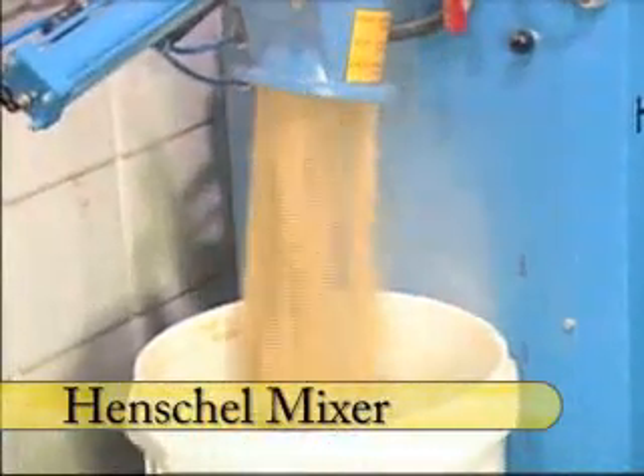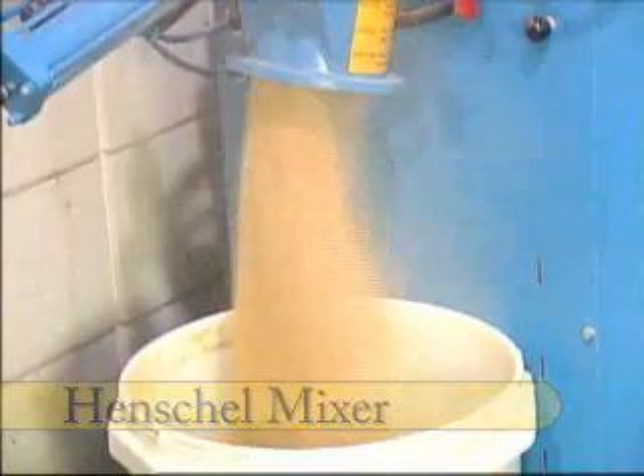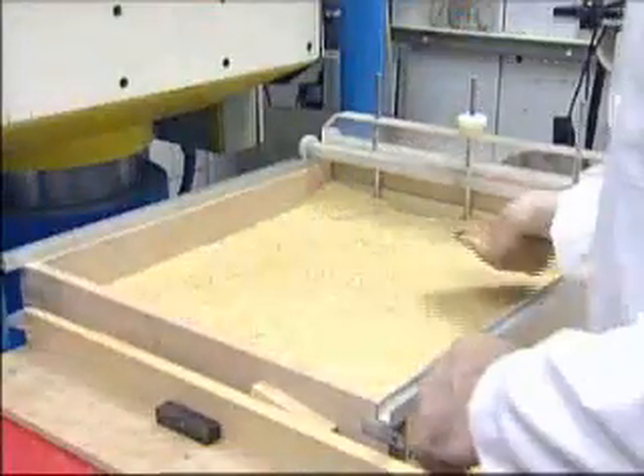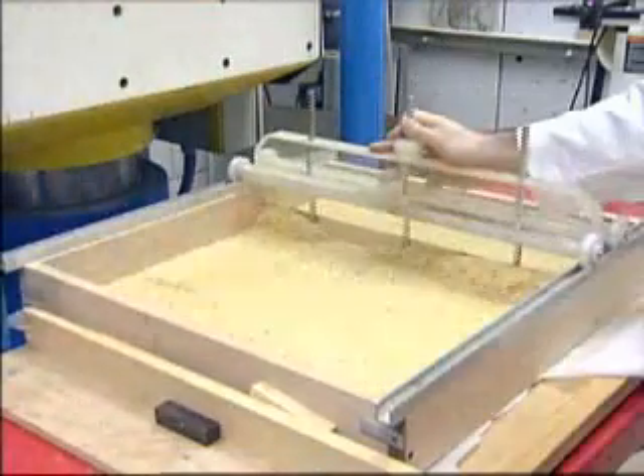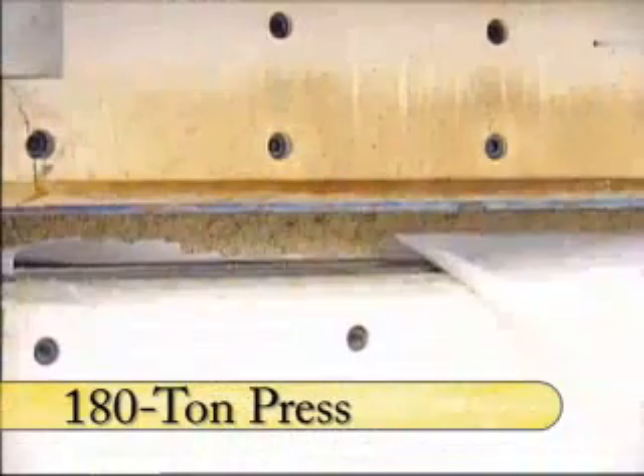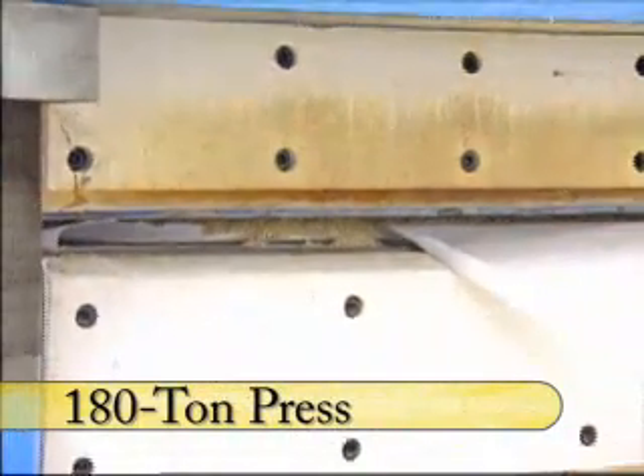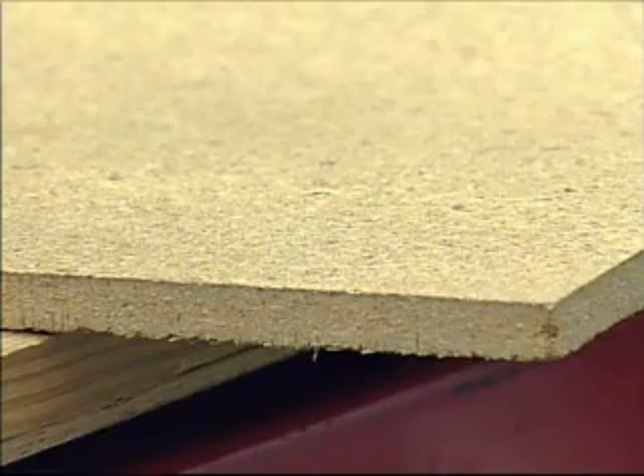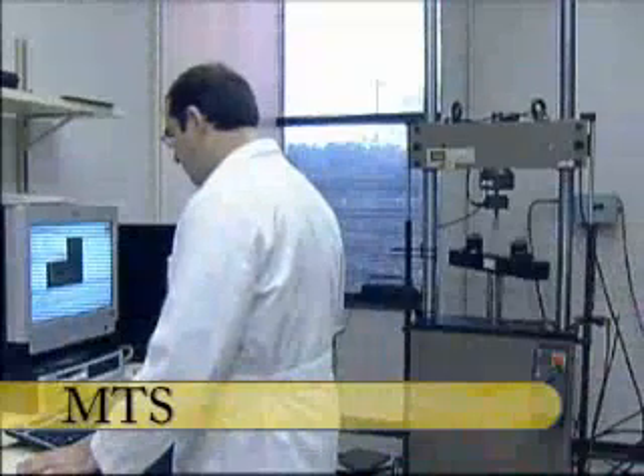The adhesive is then blended with wood furnish in a high-speed Henschel mixer. The wood furnish adhesive mixture is formed into a block and loaded into a composite press where it is heated under high pressure to 193 degrees Celsius for 7 minutes.